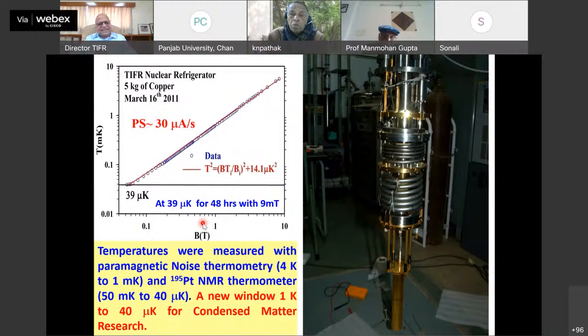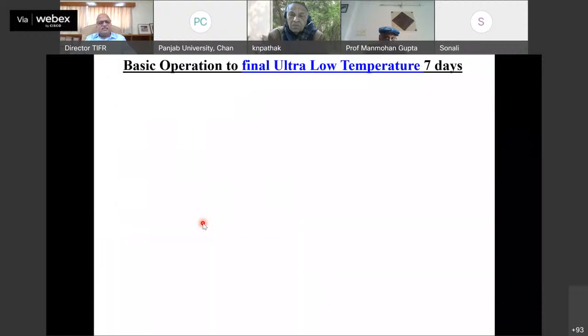So we assume that we reliably measure the temperature. Way back, more than 10 years ago, we achieved this lowest temperature of 39 microkelvin. Important thing is that you need to keep them long, at least for about 48 hours to do measurements with it. So that is what determines how good your refrigerator is. So we showed that there is a new window possible from 1K to 40 micro-K for condensed matter research.